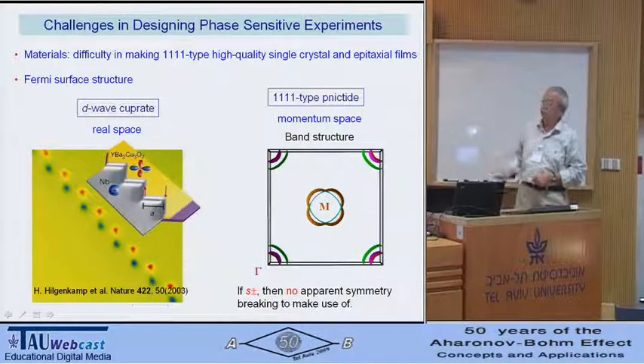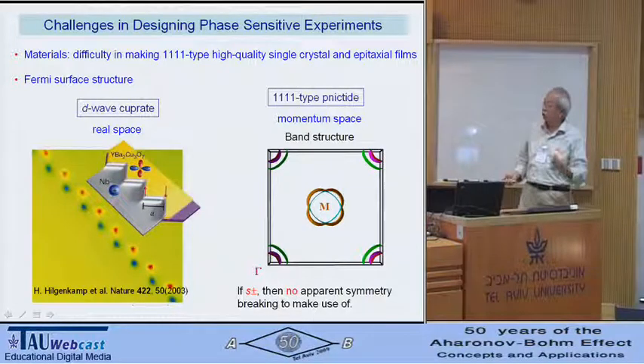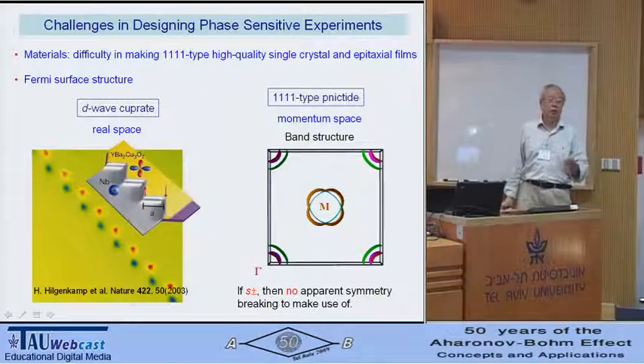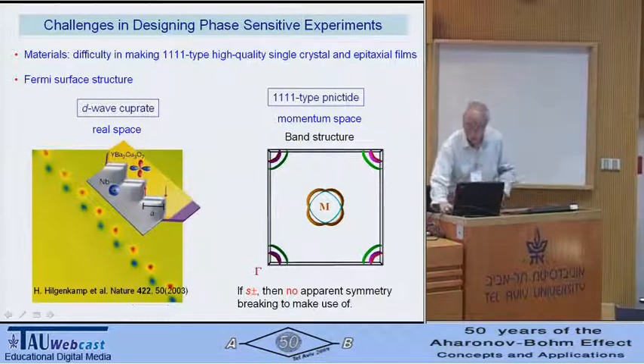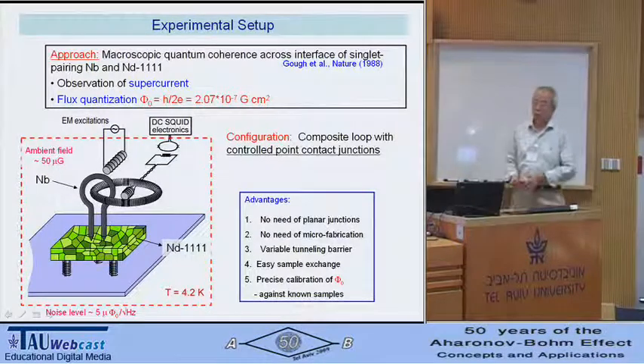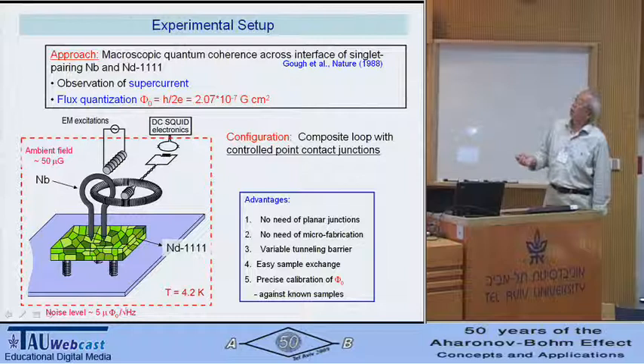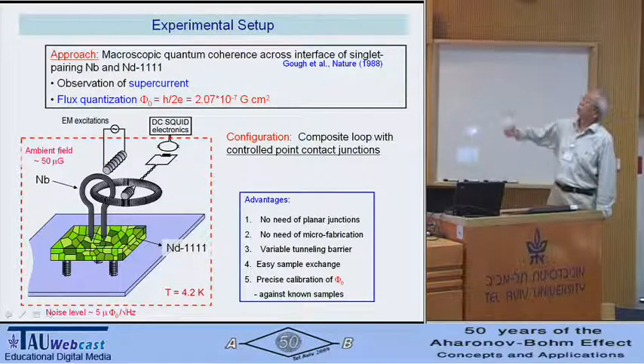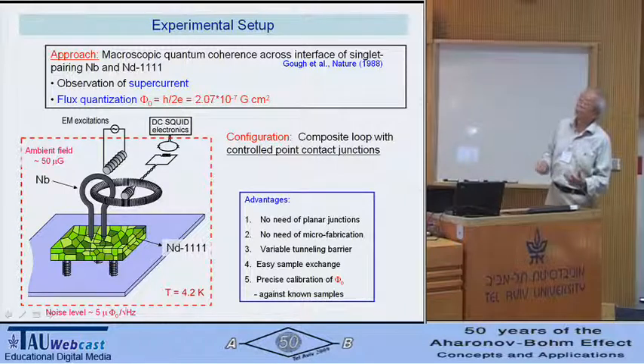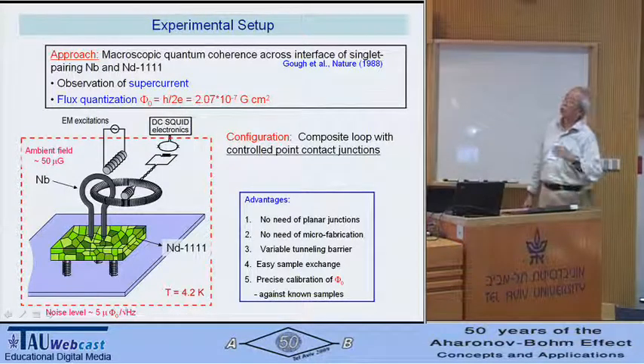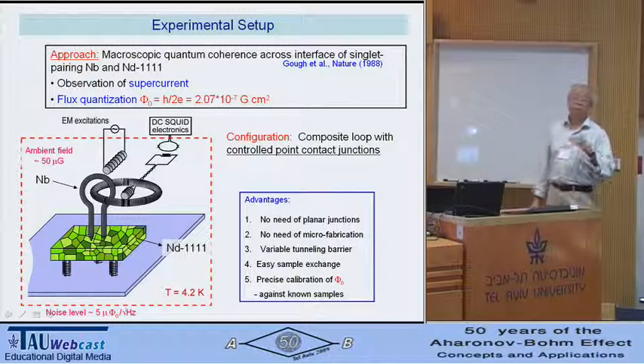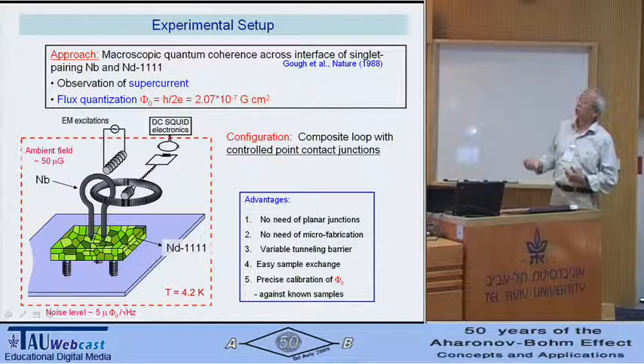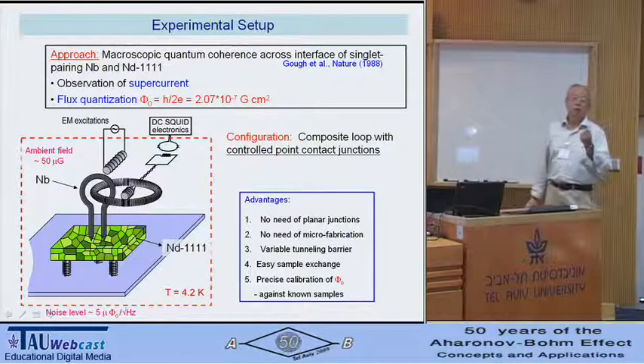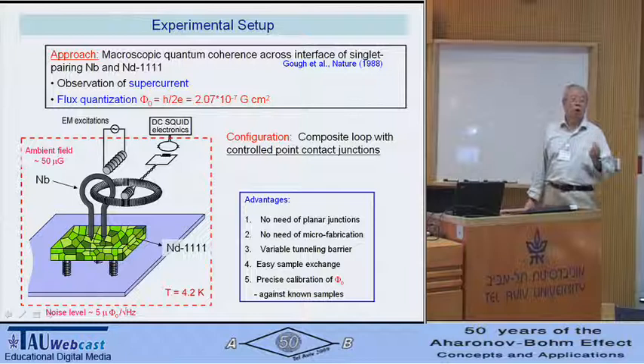Now, in this case here, it's very, very difficult. If it's S plus minus, there is no apparent symmetry breaking that you can use in designing the experiment. So that's a very, very difficult experiment to do. So our approach is this. We try to establish a macroscopic quantum coherence across the interface between the singlet pairing niobium and neodymium iron pnictide. We want to observe supercurrent. Then we want to see flux quantization. Remember, flux quantization is the finite h over 2e. That's a very, very small number. You've got to do a very good experiment in order to see it, in a low noise environment with a very sensitive instrument.